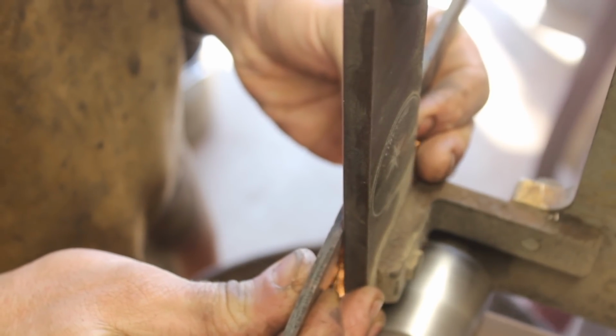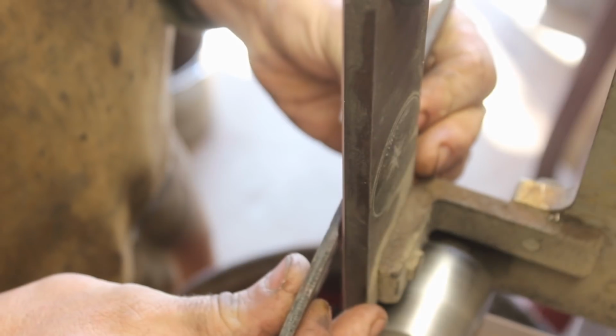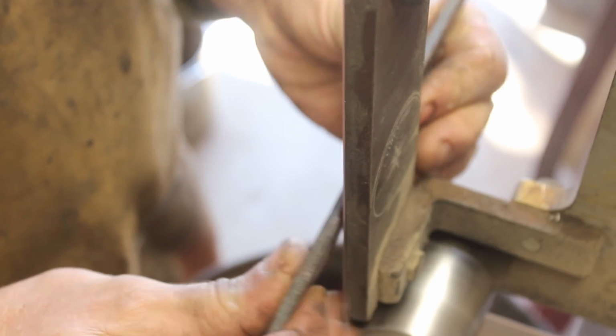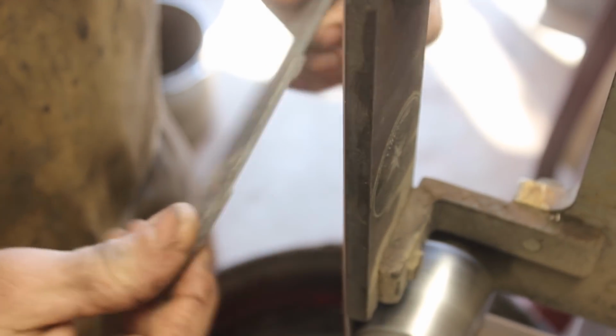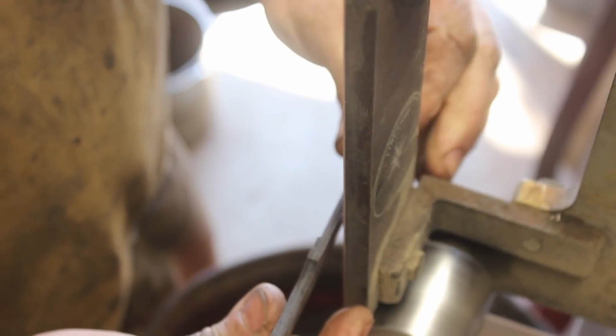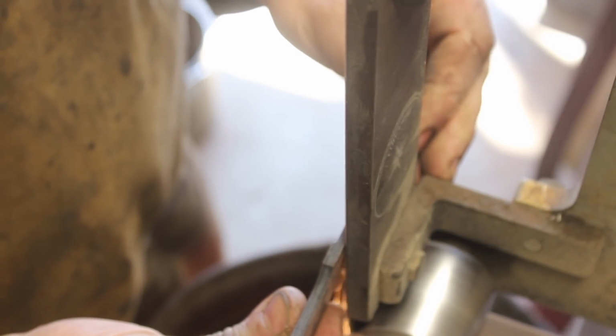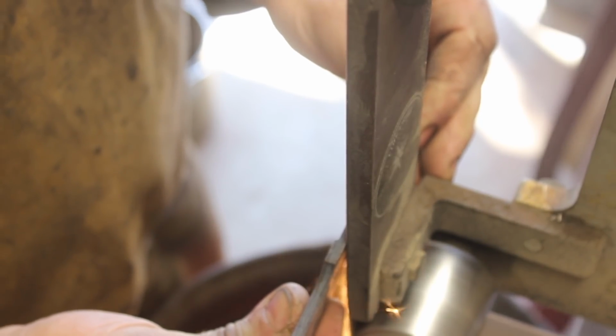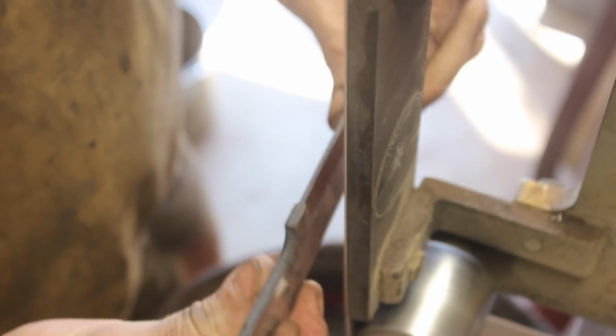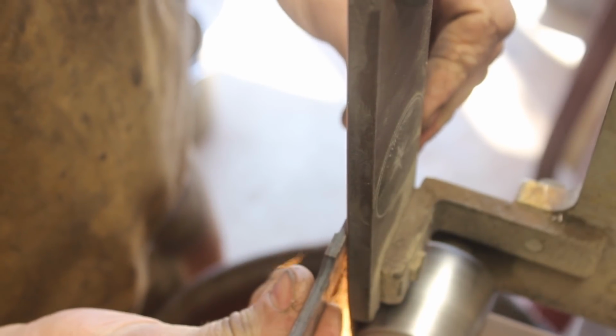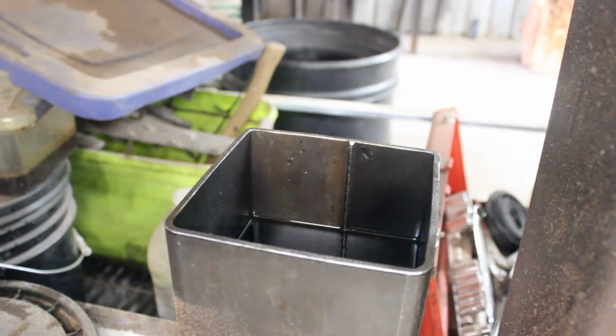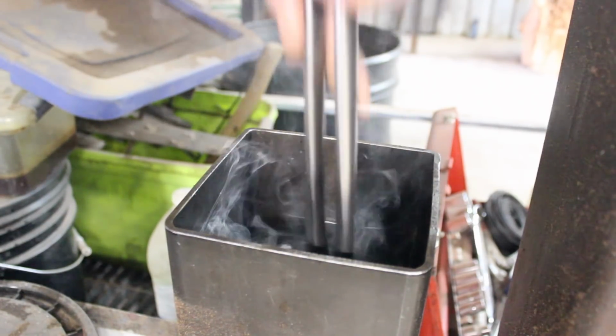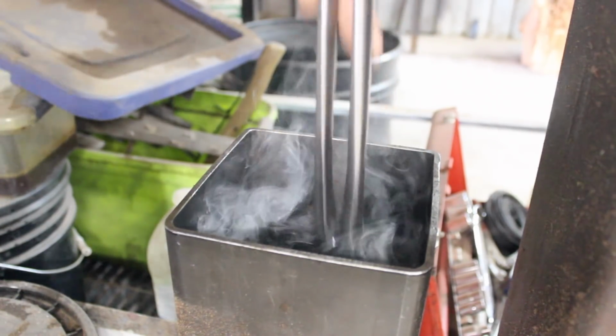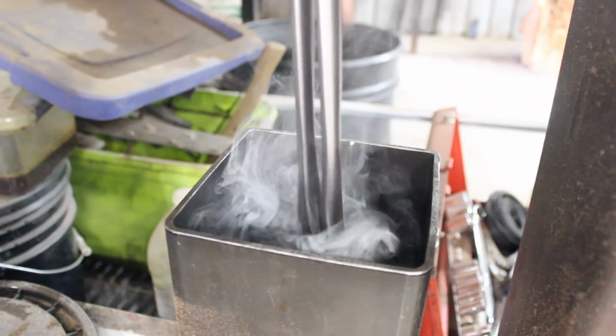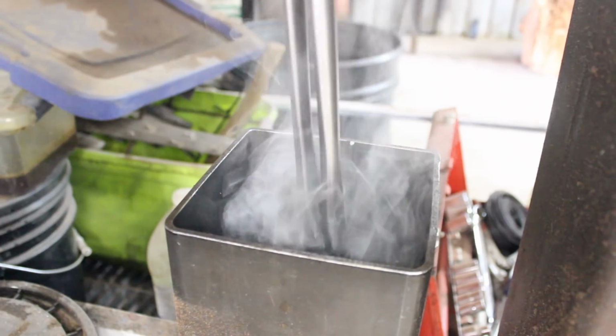So I forgot to mention that on the second try, this is actually a 1095 core, because I surmised that at the temperatures I was working it at, I should be able to get the 1095 core to stick well to the copper, just like the 1075 did. So I abandoned the 52100 core for the time being. I think it's certainly possible to use that, but the higher temperatures probably are going to be necessary for that to braze to the 52100.